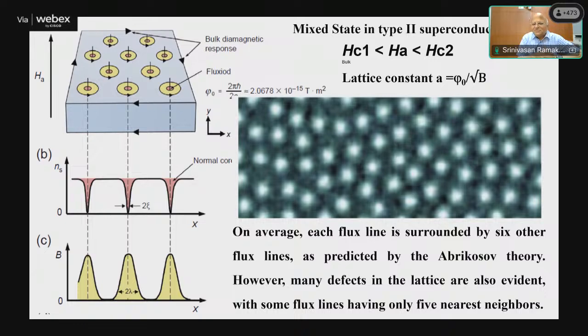And that in a sense is a hallmark of a theory, which clearly showed this, done by Abrikosov. After Ginzburg-Landau was successful in explaining many of the superconducting properties, Abrikosov calculated this mixed state, showed it to Landau, but somehow Landau was not very impressed. But then the measurements came, and Abrikosov could publish his result, showing that the magnetic field in the mixed state, that is between Hc1 and Hc2, penetrates in the form of a lattice. So it's a hallmark of a type 2 superconductor that you have a lattice whose lattice constant can be varied by simply changing the magnetic field.